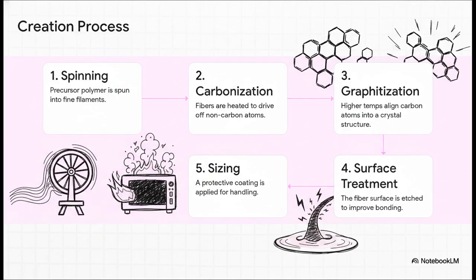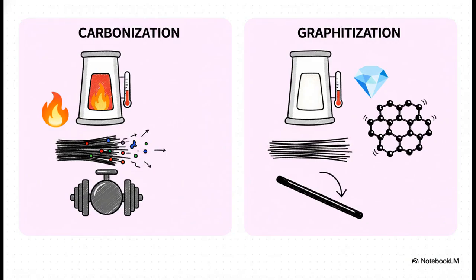Let's zoom in on that heating part for a sec. Okay, so this is super interesting. You've got carbonization and graphitization. They're both about heat, but they do totally different things. Carbonization comes first. And when I say lower temperature, we're still talking a crazy 600 to 1200 degrees Celsius. In that furnace, all the junk, the non-carbon atoms like hydrogen and nitrogen, they just get baked right out. What you're left with is what we call high-strength or HS carbon fiber.